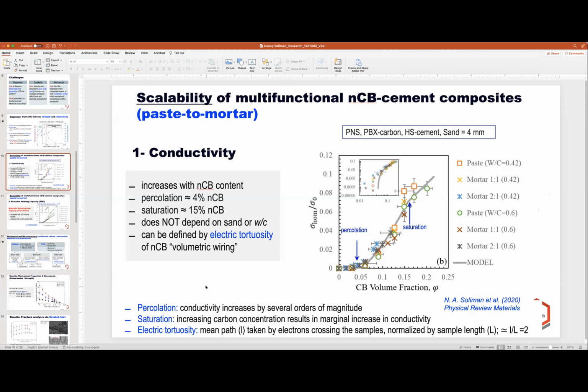Yeah. So actually the percolation threshold at 4% is very low compared to other materials, like sand, which doesn't have any aspect ratio. But unfortunately we lose the strength at microscale and the full advantage of a multifunctional material. Now we understand that the reduction in the strength is due to the de-cohesion of the material, and by that we can add some bonding agent or some functionality to the carbon black particle, which enhances the bonding between nanocarbon black and the matrix without losing the connection between the particles.